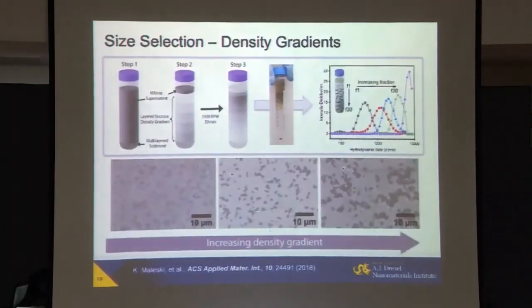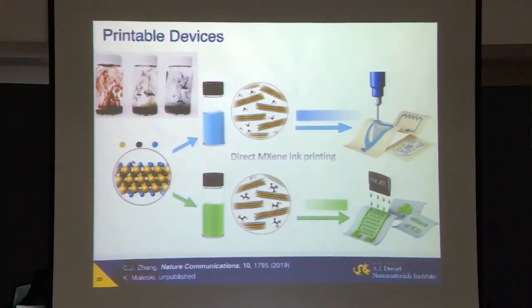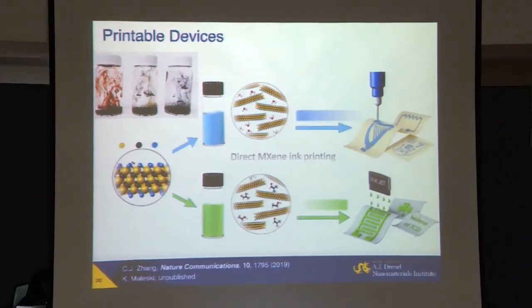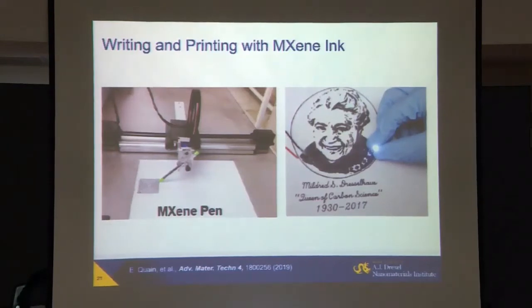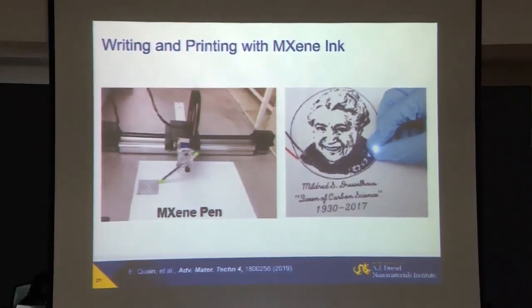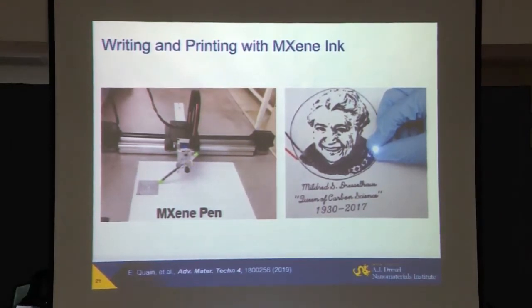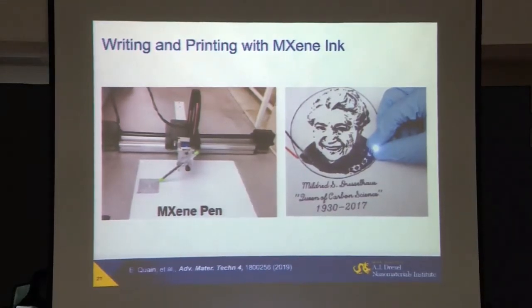And we can select them by different particle sizes for different applications, and we can print them. And again, we can print even in different colors if you want, and print devices just from aqueous ink. For example, this is a picture of Professor Mildred Dresselhaus, grand lady of carbon science, which my student printed when she passed away in 2017. Actually, it was not even printed, it was painted with a MXene automatic pen. So we can take a fountain pen, or a rollerball, and basically just fill it with this MXene ink and make a conductive pattern. You can see an LED light in contact with this picture here.